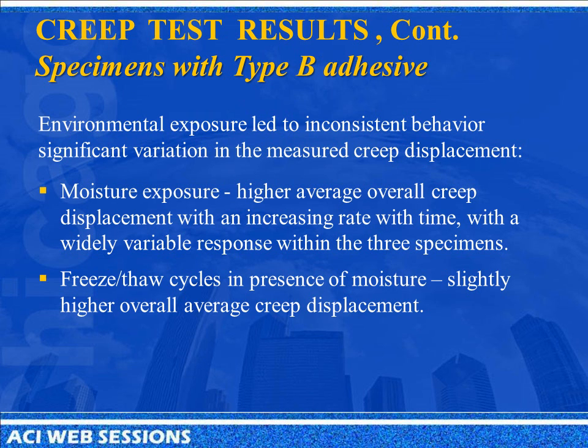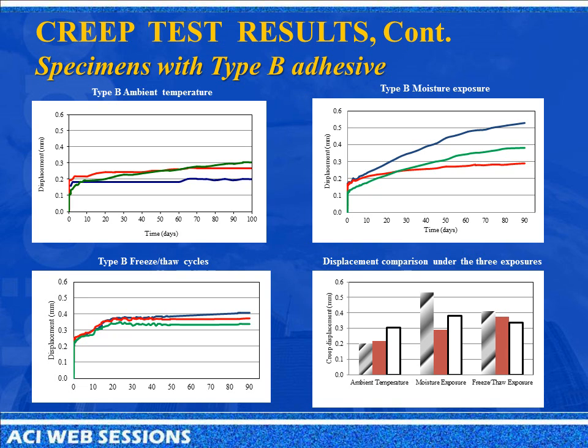For specimens with the type B adhesives, so that would be the fast-set epoxy-based adhesives. Again, similar effect when moisture is exposed, higher overall average for creep displacement with an increasing rate with time. Widely variable response, again, with the three specimens. Freeze-thaw cycles slightly increase the creep displacement. So, again, the creep displacement versus time curves for that type of adhesives. Again, you see with the moisture exposure, similar to before, inconsistencies and significant increase in creep displacement.